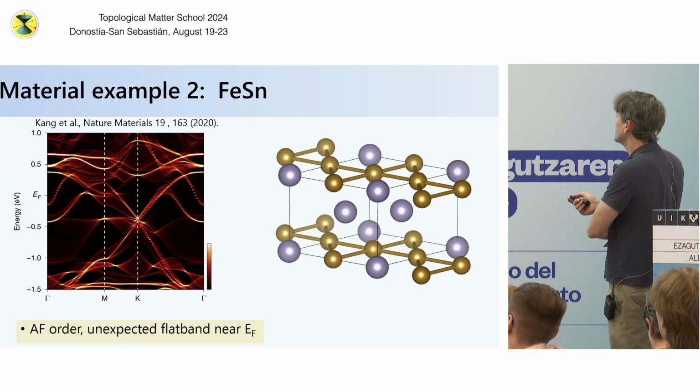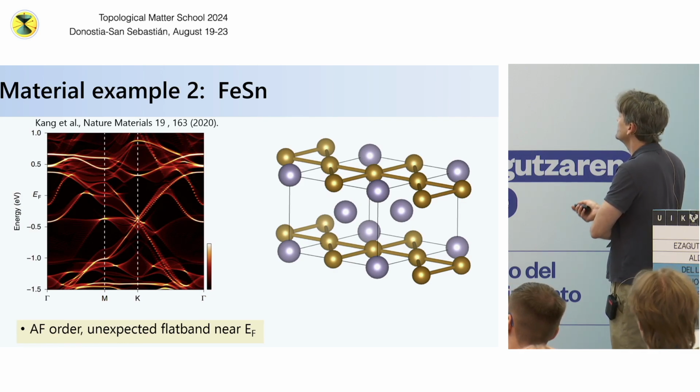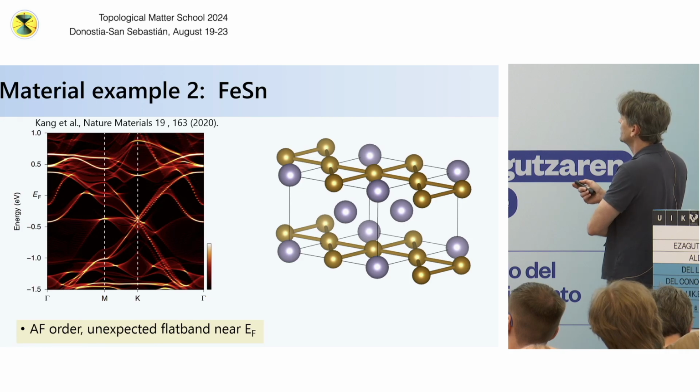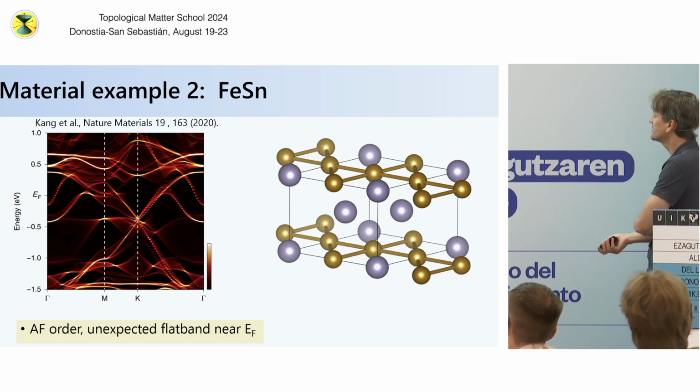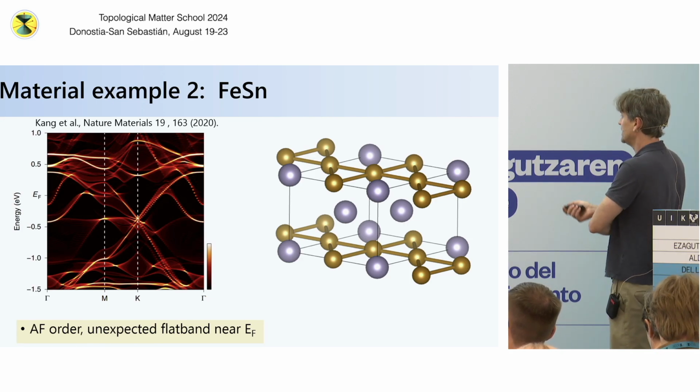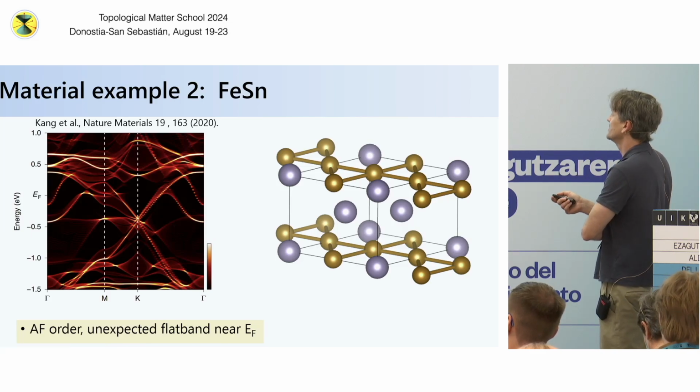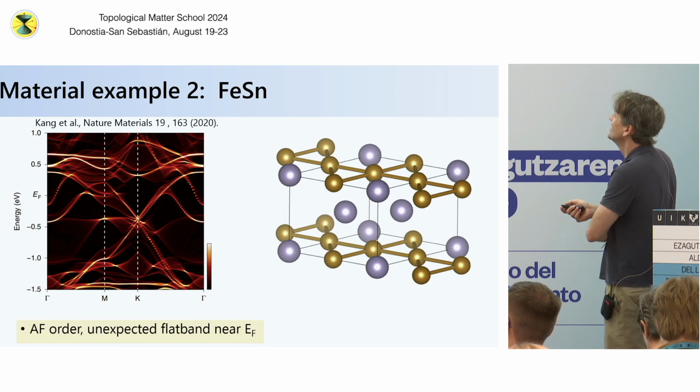And if I'm drawing the Kagome lattice on this, just doing the nearest neighbor distance, here's the iron tin lattice. This is sort of a nice prototypical structure to start from. And if you look at the DFT of this system, you can see here's the Dirac crossing at the K point. And there's a flattish band, which is down here and then down here.